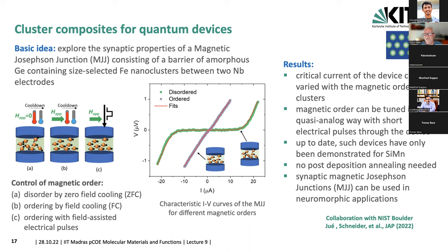And depending on how the clusters are ordered magnetically, you get different IV curves. And this is exactly what they want for this magnetic Josephson junction application. And the nice thing is that we can also control the magnetic order by the process which we use to prepare or to handle the film. And one thing would be to create disorder, so this state here, by zero field cooling. So you take a sample from room temperature, you go down to a few Kelvin without a magnetic field, or you order it with a magnetic field.